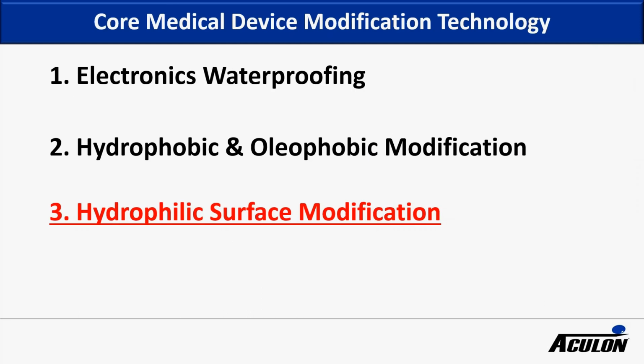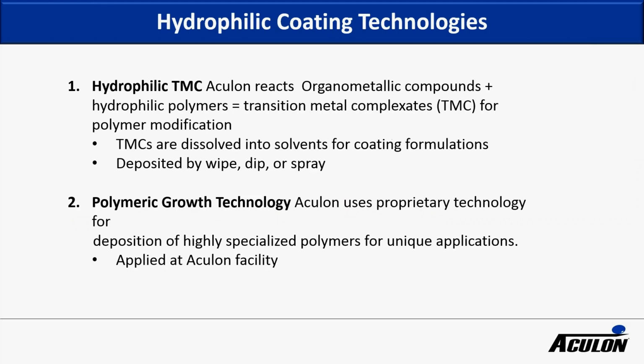Now I'd like to move to our hydrophilic surface modification technology, give you an overview of some of the treatments we have and some more examples. Here we really have two technologies. Once again, we use our transition metal complexate chemistry, where we're now taking hydrophilic polymers and reacting them with organometallics to form these transition metal complexates. They're dissolved into solvents, and then they can be deposited either by dip, wipe, or spray. We also use our polymer growth technology to make hydrophilic surfaces. We'll prime the surface with a SAM and then tether hydrophilic polymers to that surface.